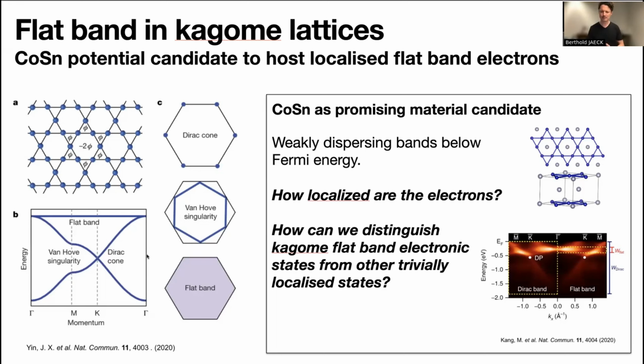Now, in the past years, some advances were made, and in particular, cobalt tin was identified as a relatively promising material candidate. As I mentioned before, this iron-tin family with a 1:1 stoichiometric ratio has the benefit that the Kagome layers are essentially stacked on top of each other in AA stacking, but separated by a stannene layer in between. This is advantageous because it suppresses or reduces the influence of these out-of-plane hoppings that would allow electrons to flee the jail.